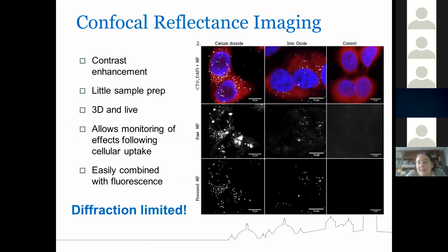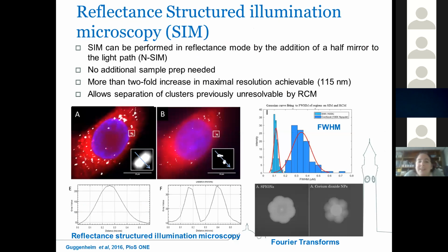But what you see in some of those is what looks like clusters of particles. One of the questions we had was, could we resolve those better to see, are the particles agglomerated, or is it just that the resolution makes it appear that they're all together? So one of the ways we've looked at is reflectance structured illumination microscopy, which again we can do in the reflectance mode, but it allows separation of clusters that were unresolvable by the reflectance confocal microscopy. So again, it just gives us a bit more resolution, and a signal that in the reflectance confocal appeared as one big blob, under the SIM, the structured illumination microscopy, actually gets separated out into distinct regions of interest. So we can really get much better resolution in the images.